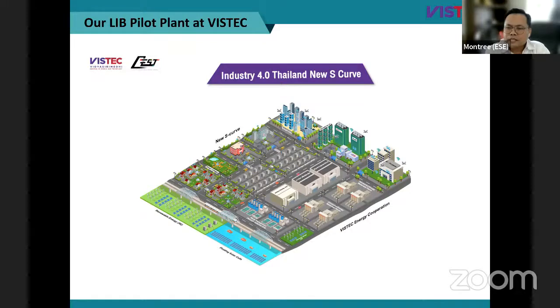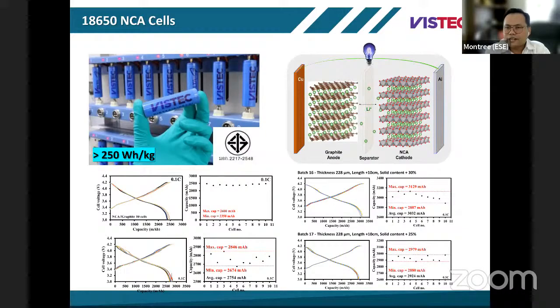Yeah, that is what we hope. Looking at VISTEC in detail, at that time we got support from the Ministry of Energy. They required us to have a really high standard battery, and we needed to pass everything. Here we achieve 250 watt hour per kilogram by using, say, NCA as the cathode material, and we do modification by encapsulation. The shell material can be carbon or other material. This is our technology using mechanical fusion, which is scalable without chemicals.